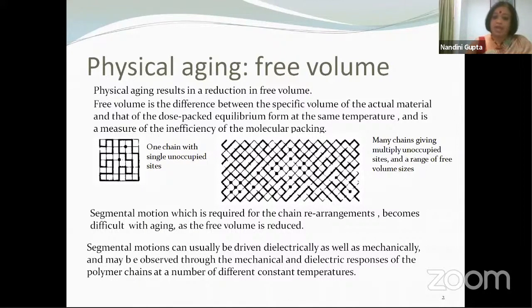So therefore, if you look at the dielectric response of a material over time at the same temperature, the dielectric response will change because the segmental motions of the polymer chains will change, and because the polymeric motions will change because of the reduction in free volume. So this gives us a way of estimating the physical aging of a dielectric.